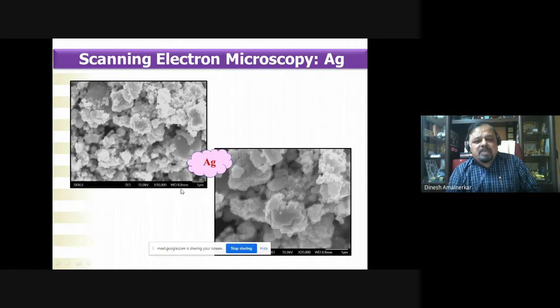Okay, the same thing is true with the Roupyabhasma sample. Here we could see some kind of faceted grooves. We can see irregular shapes and particles of silver. The picture lacks contrast. We did not get very good atomic number contrast because of the secondary electron imaging and the charging. But here also we observed the particles are embedded in an insulating inorganic matrix, which is amorphous in nature because nothing has been detected in the X-ray diffraction.